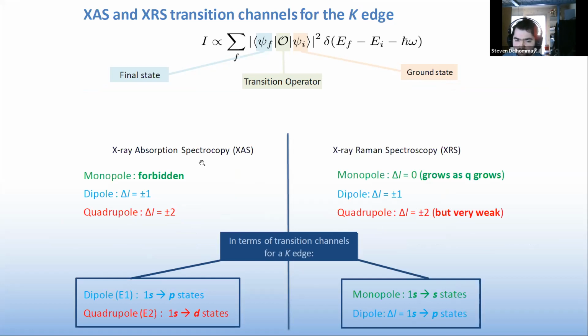For X-ray absorption, we just have the dipole and quadrupole channel that are ruled by these two specific transition rules. And that means that for this spectroscopy technique, we have access to 1s to p and 1s to d transitions if we are looking at the K edge. For X-ray Raman spectroscopy or scattering, we have access to all these three channels, even though in this work, the quadrupole channel is going to be very weak, so it's actually not going to be here. So we have access to the monopole and dipole channel, that is to say 1s to s transitions and 1s to p transitions.